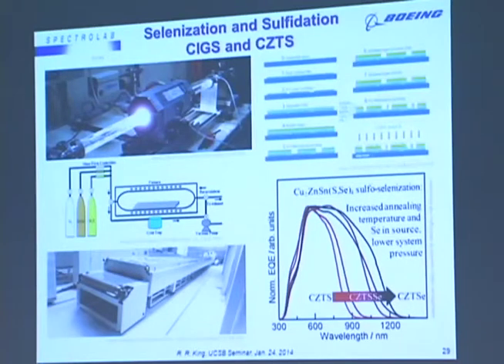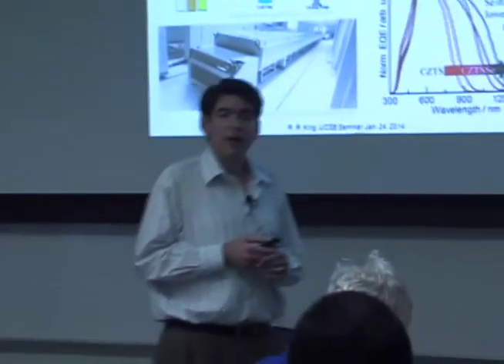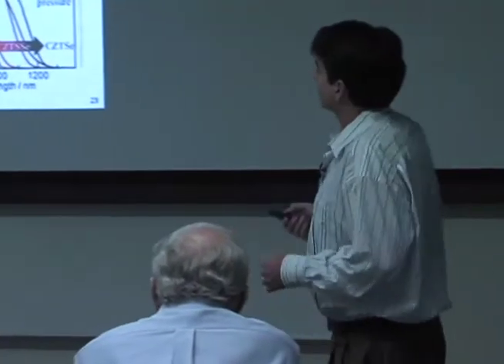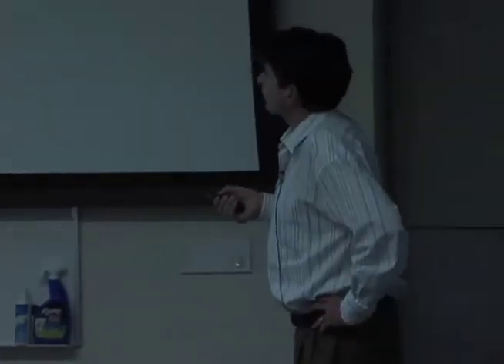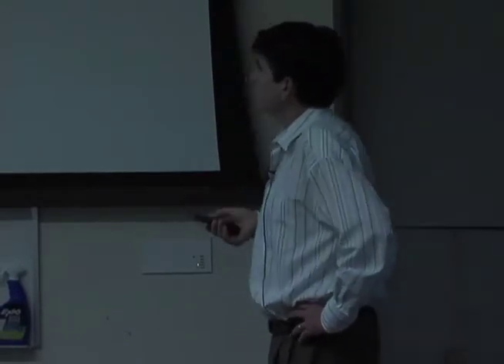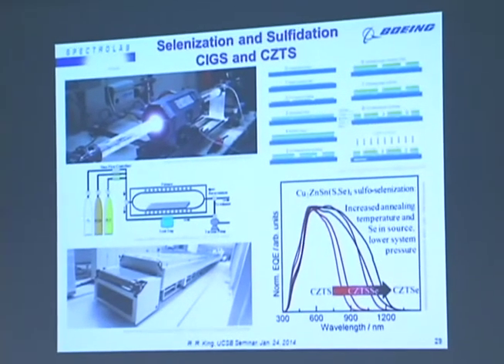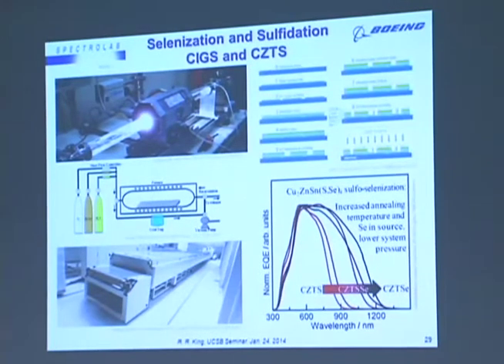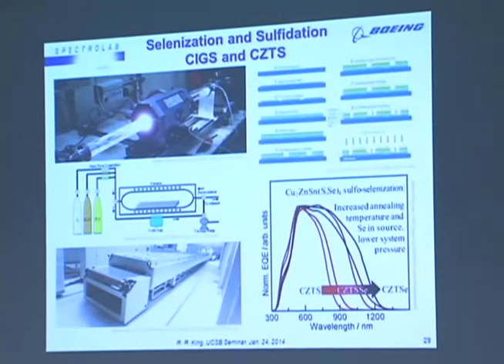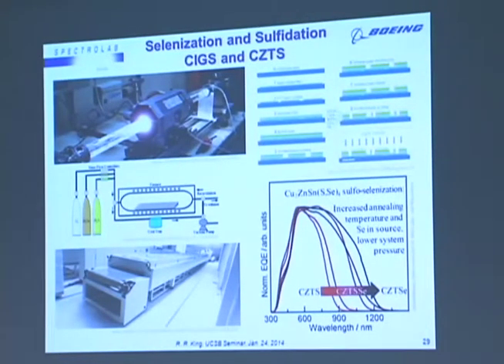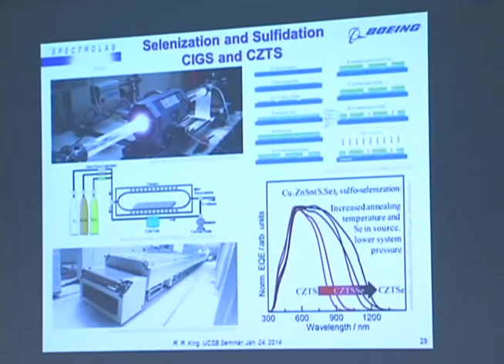For growing some of the more experimental and more highly defective polycrystalline compound semiconductors, like copper indium diselenide, we often use selenization and sulfidation reactions to form CIGS and the kesterites. So it's a relatively simple setup in which metals are deposited onto molybdenum film on glass typically, and then the copper, gallium, indium, and other precursor metals associated with the CIGS solar cell material are deposited, and then those are reacted in a hydrogen selenide or hydrogen sulfide ambient at elevated temperatures. So it's a relatively simple reactive furnace setup that can result in some remarkably high efficiency solar cells.